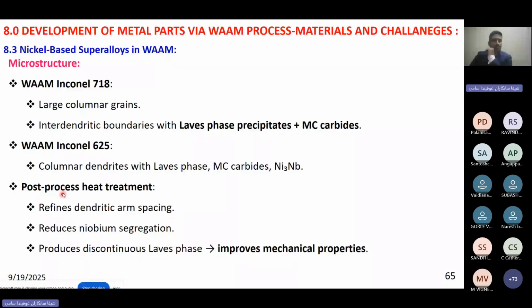In the nickel-based alloy, mostly people observed large columnar grains, and they observed some Laves phase, some precipitates, metal carbides also. These are the structures they formed: columnar grain structure and interdendritic boundary with Laves phases, some second phases, some metal carbides. For example, in Inconel 625, they observed a columnar dendritic structure with the Laves phase, metal carbides, and some nickel niobium intermetallic phases also. So in order to improve the product, they did some post-process heat treatment, by which they refined the dendritic arm size.